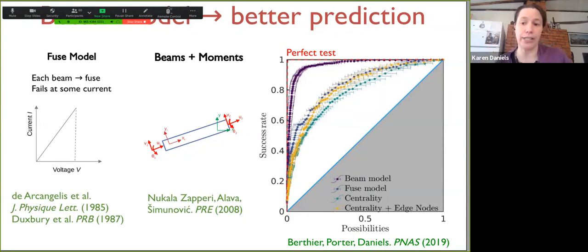So if you make that analogy and you predict where things are going to fail, that's actually the blue lines, just very close to the yellow lines, right? So this fuse model has a notion of a failure criteria and having to resist a load, and it doesn't do that much better than just topology alone. You have to actually put in the physics, that you have actual beams with actual moments that support stress, and then you can start to get something much closer to the perfect test. But you don't need a lot of physics to do pretty well.